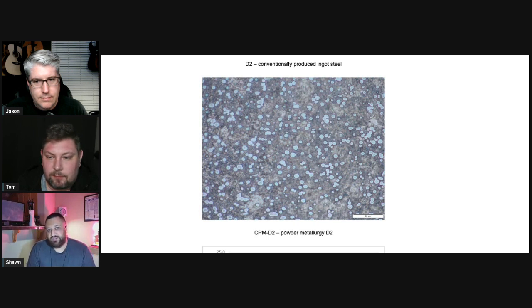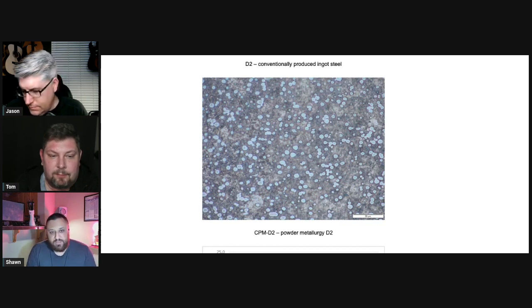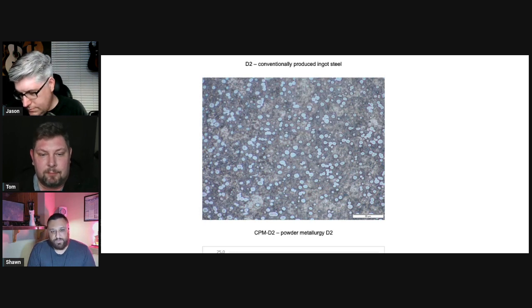And then they anneal it, and then we buy it as bar stock, and it'll have these much finer carbides right here, because the carbides didn't get a chance to grow from the slow cooling of the ingot, because it was rapidly cooled. So these carbides didn't get a chance to grow from the molten condition. And so we have much finer carbides here, but let's not kid ourselves with CPM D2. These carbides aren't as fine as something that has maybe vanadium carbides and things like that, because those carbides are going to be significantly finer even with the same PM process, which is very interesting.